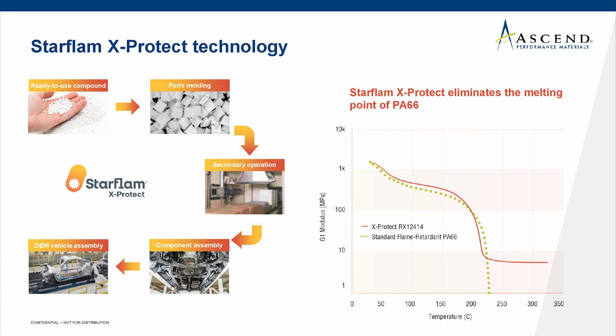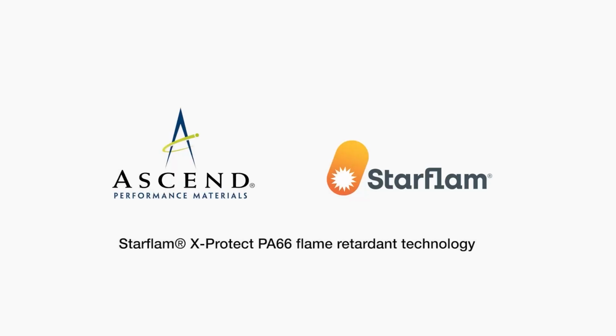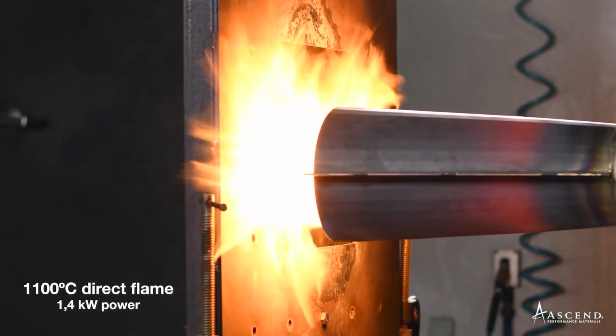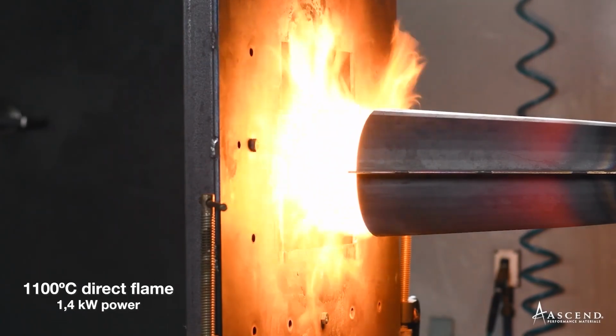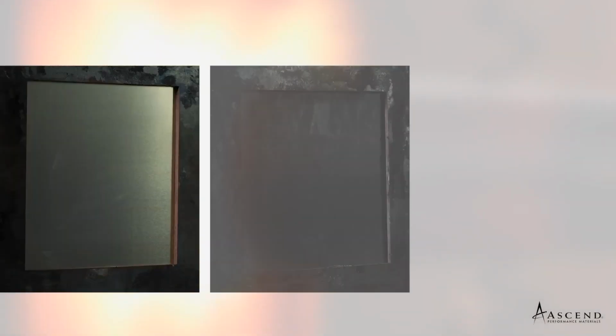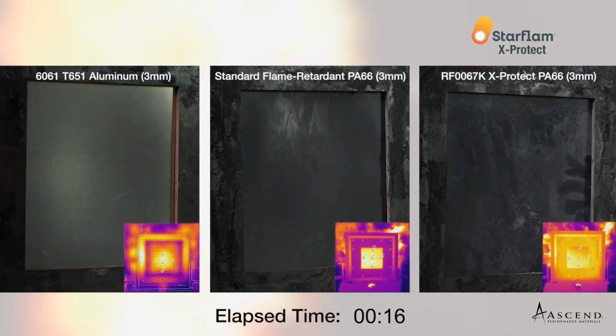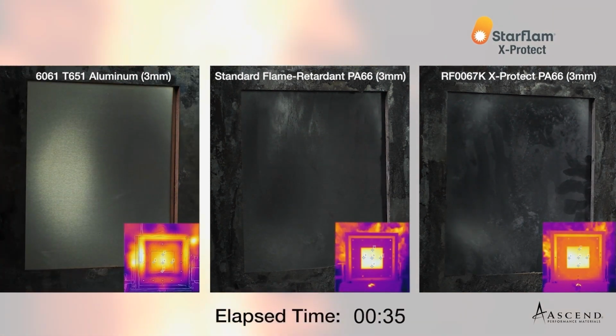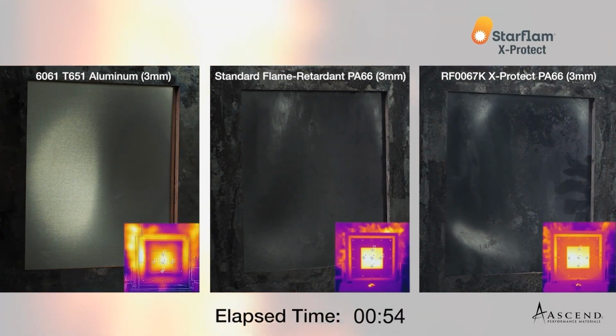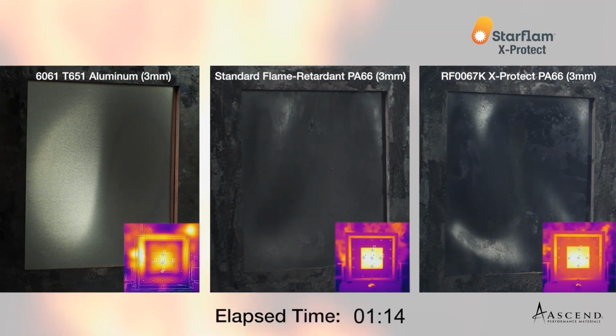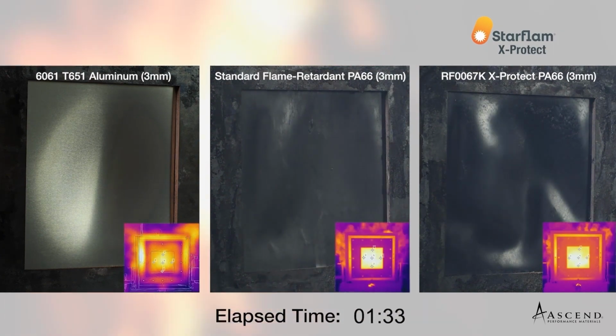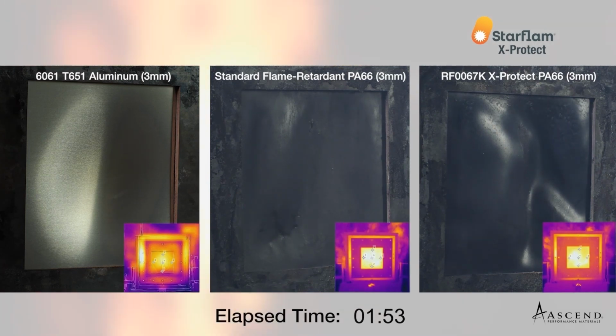But in the following couple of minutes, we want to show you a video that highlights what the material does when we're exposing it to thermal runaway conditions. Yes, here we go. So what we did is we tested a few materials in a torch exposure. The torch in this case was a serious burner, so 1.4 kilowatt power and 1100 degrees C calibrated temperature. And we're comparing an automotive grade aluminum, a regular flame retardant glass fiber reinforced PA66 in the middle, and Starflam X Protect on the right hand side. Both PA66 grades are glass fiber reinforced and all samples have 3 millimeter thickness.